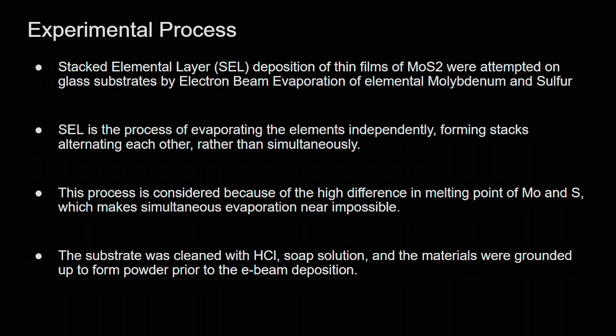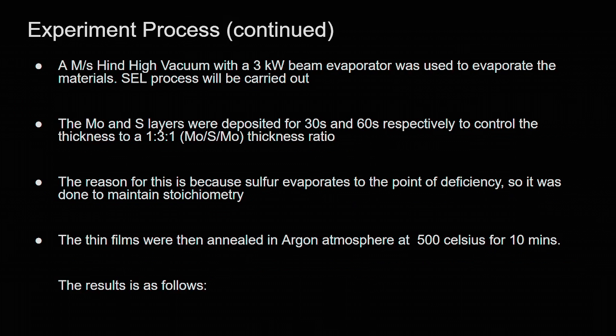This process is considered due to the high difference of melting points of Mo and S, which makes simultaneous evaporation near impossible. Before the process was begun, the substrate was cleaned with an HCl soap solution. A high vacuum with a 3 kilowatt beam evaporator was used to evaporate the materials.